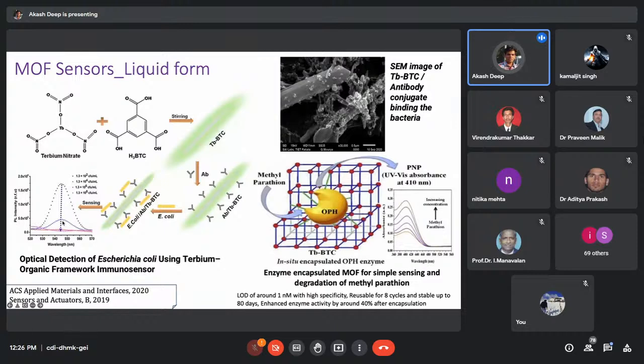So this is a very simple way of detecting the concentration of bacteria in a sample. In this case, we tested some juice samples and milk samples, and we were able to detect the presence of bacteria to as low as 13 colonies per ml. This is how the bacteria is interacting with our nanomaterial. It's shown here. You can see small rods. They are modified with the antibodies, and these bigger rods are basically the bacteria that have been captured by our nanomaterial, which is immobilized with the antibodies.